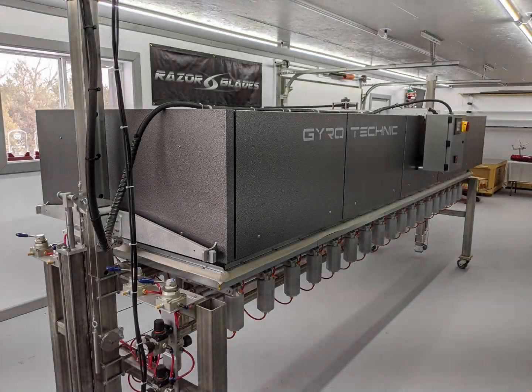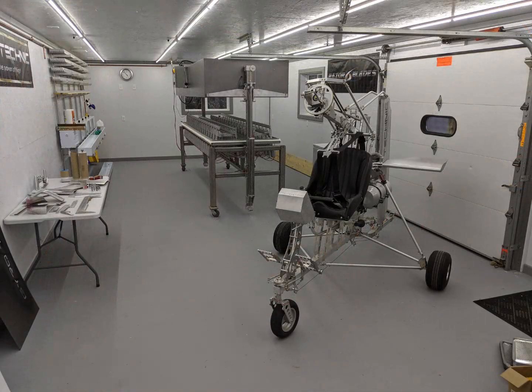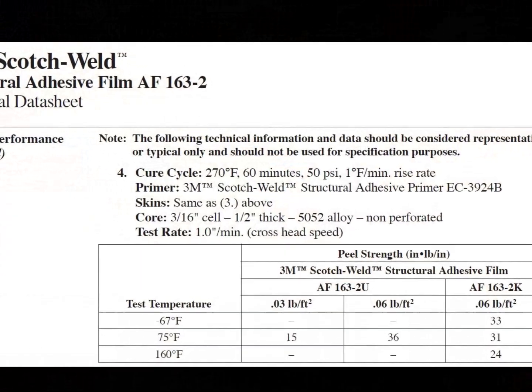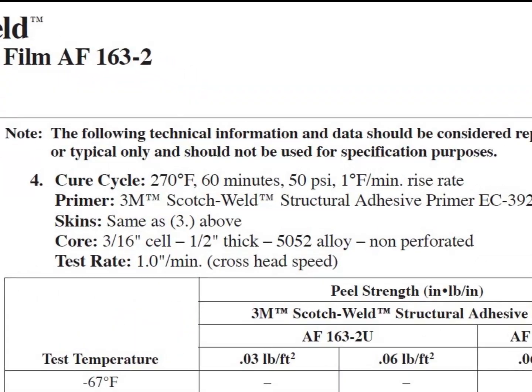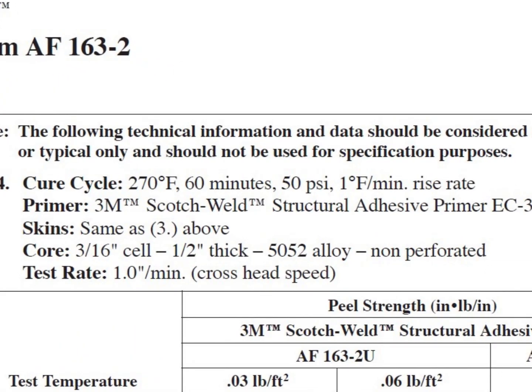The heart and soul of the whole blade assembly process is, of course, the curing oven. Here we built an addition onto our machine shop just for this process, which houses the curing oven, the etching process, and related activities. This entire system was built around the adhesive, basically to meet the requirements of a 270-degree cycle for a 60-minute soak time, clamped at 50 psi with a 1 degree per minute rise rate.